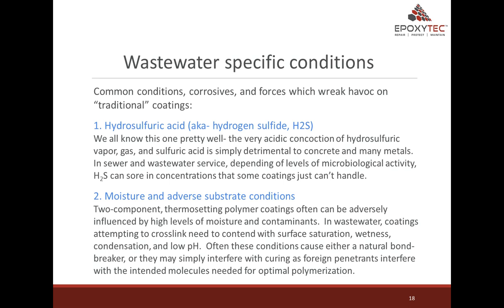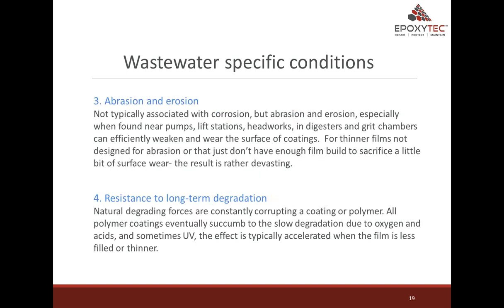Two-component thermosetting polymer coatings often can be adversely influenced by high levels of moisture and contaminants. In wastewater, coatings attempting to cross-link need to contend with surface saturation, wetness, condensation, and low pH. Often these conditions cause either a natural bond breaker or they may simply interfere with curing, as foreign penetrants interfere with the intended molecules needed for optimal polymerization.